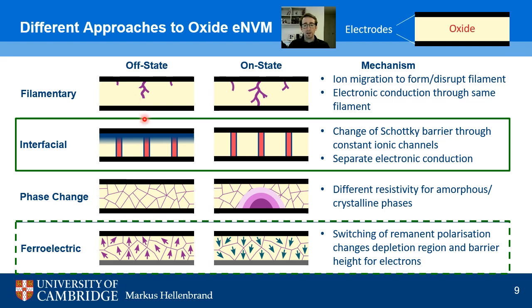Now, in contrast to that, a different approach would be called filamentary non-volatile memory. It uses the same basic cell, so just 2 electrodes with an oxide in between. But here the resistance is now not controlled by the interface, but instead by a filament through the material. This is typically realized by oxygen vacancies as well, but instead of accumulating them at one interface or depleting them, they form a conduction path from one electrode to the other. And in this case, again, we can realize a state 0 and a state 1.